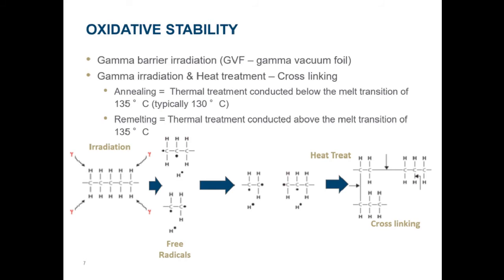Barrier packaging was designed to prevent oxygen from entering the package, allowing the material to maintain oxidative stability while on the shelf. During this time, recombination and/or cross-linking of the broken molecular bonds is encouraged due to the lack of oxygen. However, once the package is opened, the remaining free radicals are exposed and may combine with oxygen throughout the life of the implant. Retrievals of implants that are barrier packaged, such as the GVF and ARCOM, have been shown to oxidize in the body.